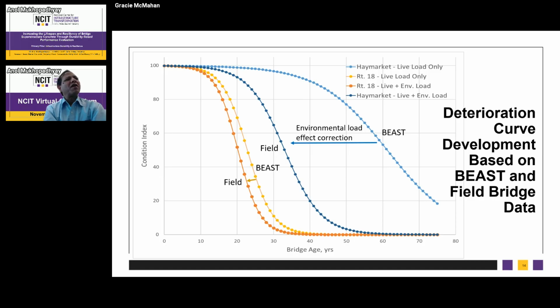You see here the BEAST curve is the reference curve, and there is a correction for the environment, that's the left curve. So that's an actual evaluation. They did BEAST, then tried to predict the load-only deterioration curve, and then did the environmental correction. And then the left bridge is the RT18 bridge, where the BEAST curve is compared with the field curve. That correction was actually incorporated without doing the NDT evaluation of that particular bridge. So that is the beauty. That means on the left side, the 2 curves, like for RT18, can be generated without going to the field, because of the advantage of the BEAST facilities.